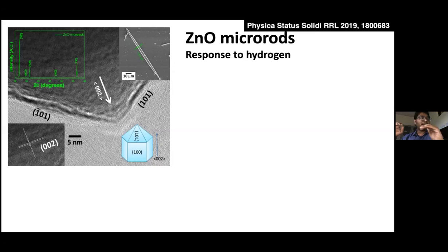Now, we looked at the response of the ZnO, but these ZnO needles, as you can see in the scanning electron microscope image here, are single crystal like needles, and they are fairly large in size, of the order of a few microns. So it is something which has very long range, a very large crystal, and the grain boundary effect I was talking about is hardly 2 to 5 nanometers. That is insignificantly small compared to the transport within the grain or within the crystal.